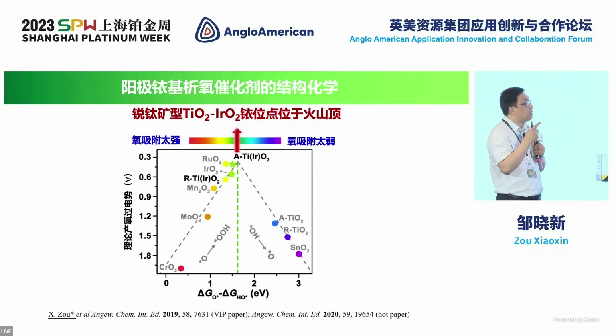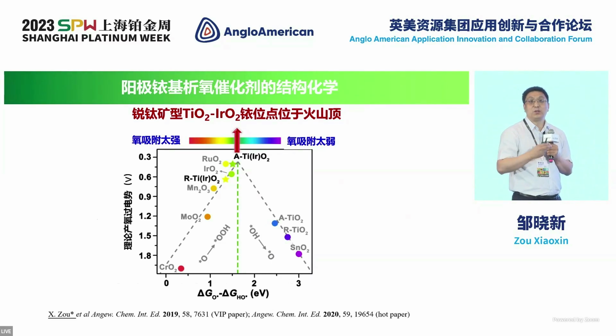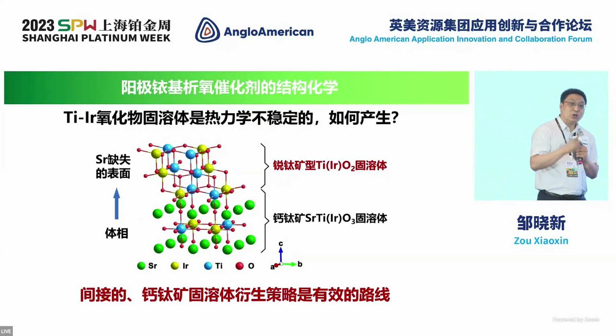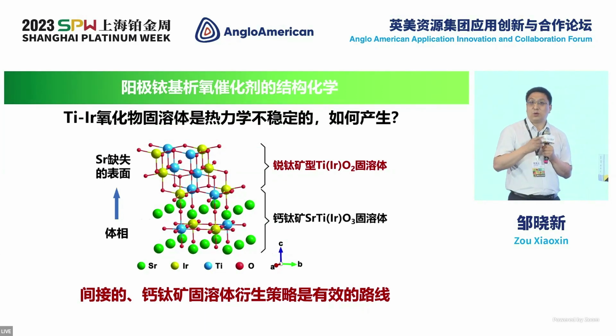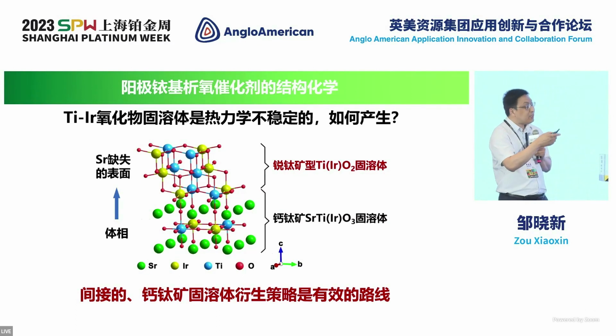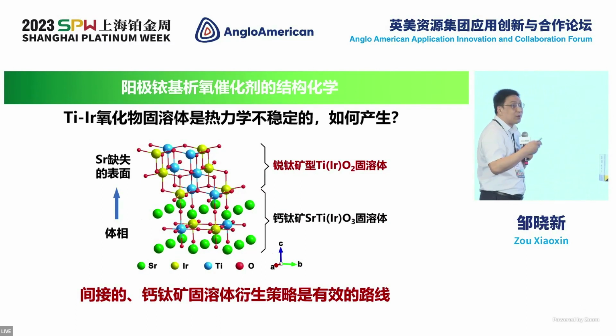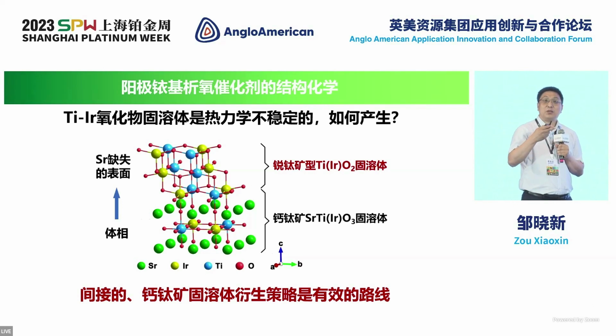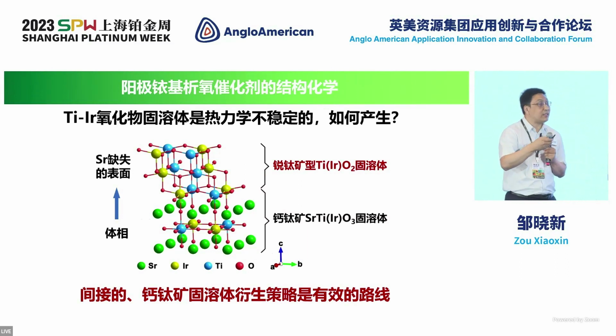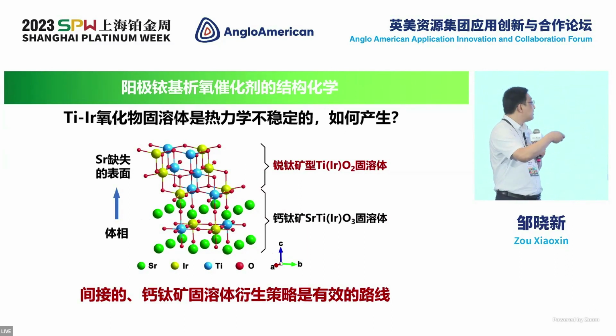If you look at the structure of the solid solution, you can see that in the iridium site, the oxygen absorption power is pretty balanced. So if we are able to make the solid solution, then we can produce a highly active catalyst. I have said that. But the problem is that it's a metastable phase. So from the thermal perspective, it is not stable.